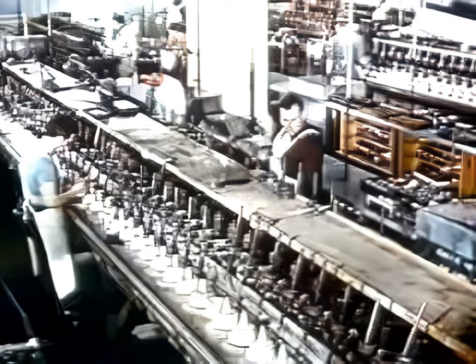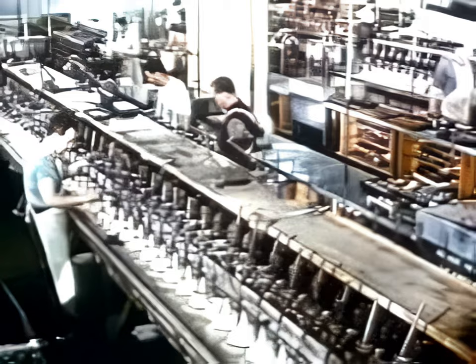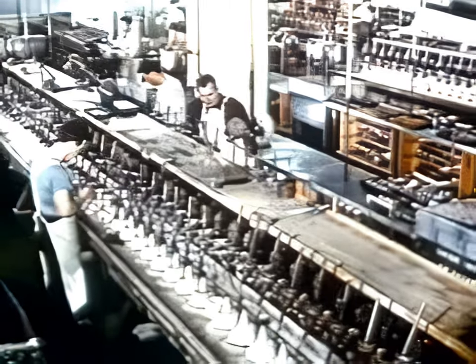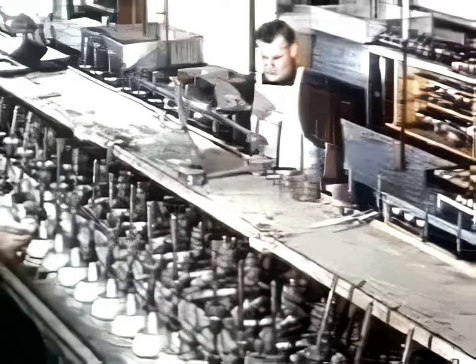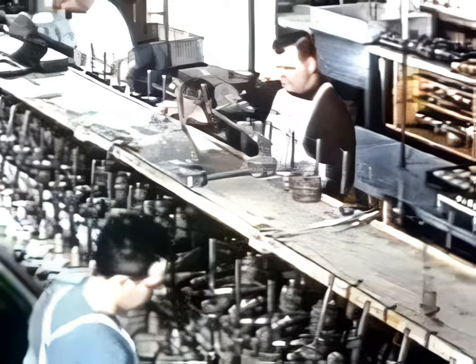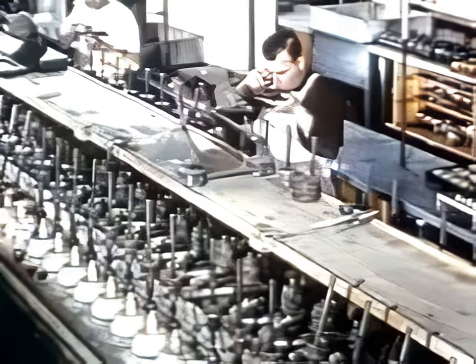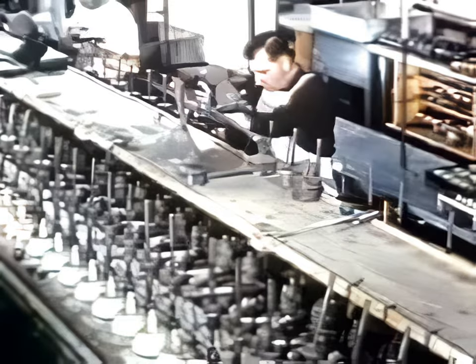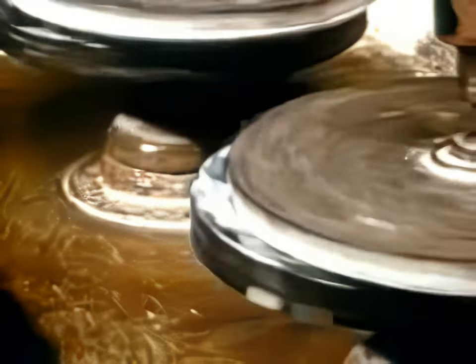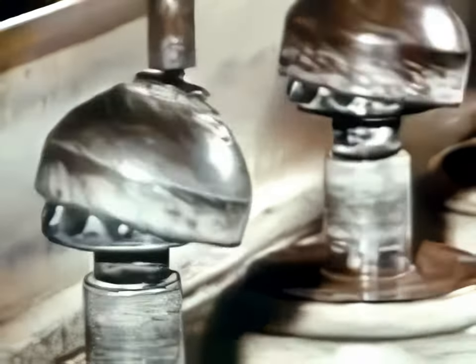This is a portion of the polishing area, a small section of almost a full acre where this precision work is carried on. And of course, the air in these rooms must be carefully washed and filtered to eliminate the danger of large dust particles which could scratch the lenses. There are as many as 5,000 lenses being polished here, and many take more than a full 8-hour day to be completed. For here, the everyday standard of measurement is in millionths of an inch.